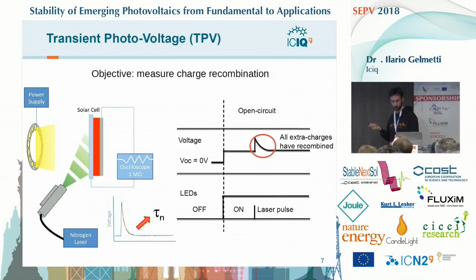So for studying the recombination, we use the transient photovoltage, which basically consists in a cell kept in open circuit condition, measuring the open circuit voltage through an oscilloscope. We shine a constant light intensity and we add a small perturbation through a laser pulse. This small perturbation produces a small amount of extra charge, which will be observed as an increase in the open circuit voltage. So the open circuit voltage will grow, and when the light pulse is over, it will relax to the steady state condition as it was before the light pulse. This dynamic can usually be fit by an exponential decay and can give information on the lifetime of the charges, at least from our interpretation.